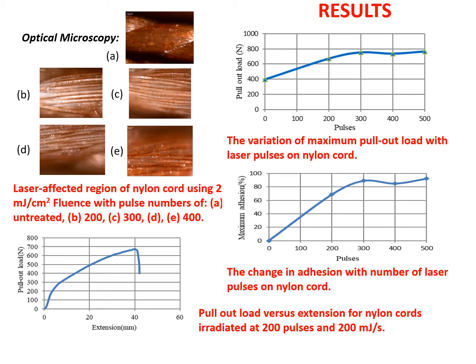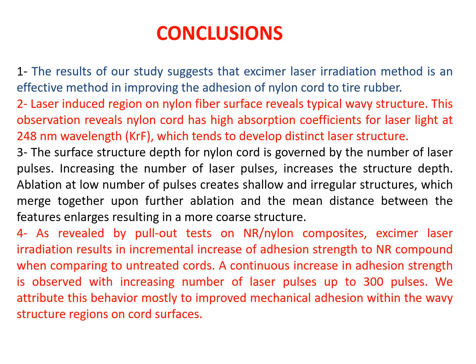The upper graph shows that the pull-out load increases monotonically until 300 pulses and then levels off. It becomes approximately constant. The lower of the curves shows the variation of maximum adhesion with pulses. Again, the maximum adhesion increases monotonically up to 300 pulses, after which an approximately level adhesion force is obtained. So in conclusion, we can say that the results of our study suggest that the excimer laser irradiation method is an effective method in improving the adhesion of nylon cord to tire rubber.